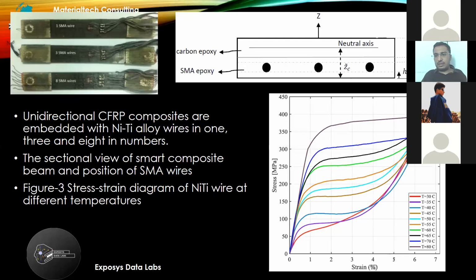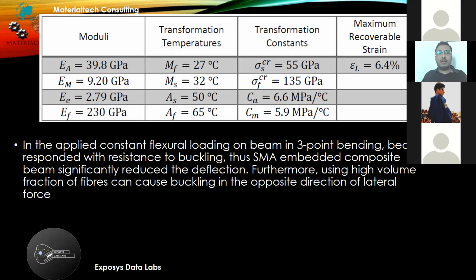Now this also gives you different temperature levels. It gives you the stress-strain curves from 30 degrees Celsius, that is room temperature, to 80 degrees Celsius. That's what we have characterized. Though we obtained it from commercially available SMA, we have trained it and tried to achieve how it is going to benefit structural health or structural strength. The shape memory wires are giving these stresses at different temperatures. So this characterization and the moduli of the investigations are shown here.